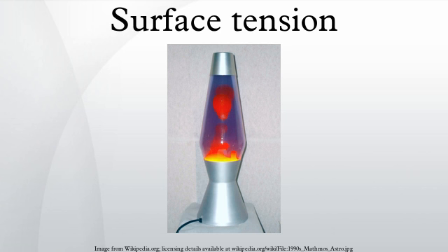Du Noüy-Padday method. A miniaturized version of the Du Noüy method uses a small diameter metal needle instead of a ring, in combination with a high sensitivity microbalance to record maximum pull. The advantage of this method is that very small sample volumes can be measured with very high precision, without the need to correct for buoyancy. Further, the measurement can be performed very quickly, minimally in about 20 seconds. First commercial multi-channel tensiometers, CMC, were recently built based on this principle.